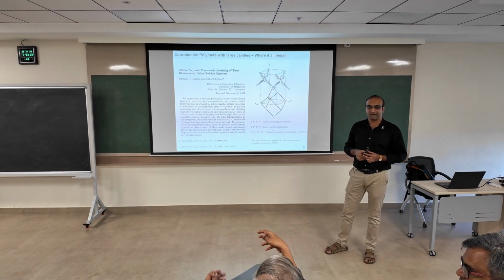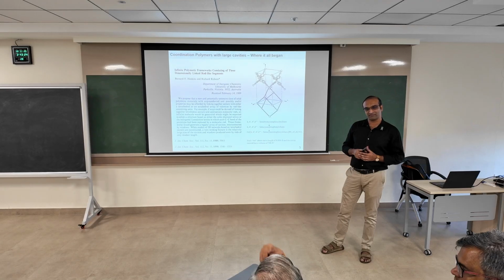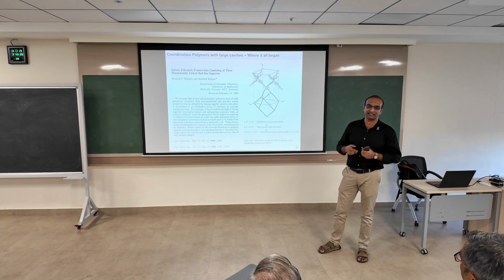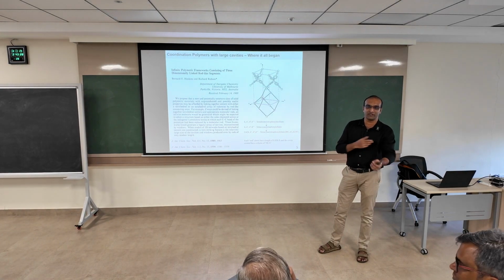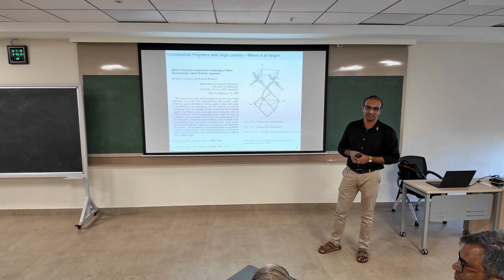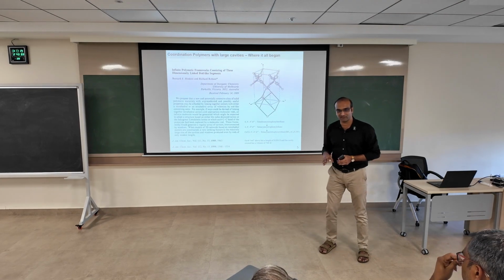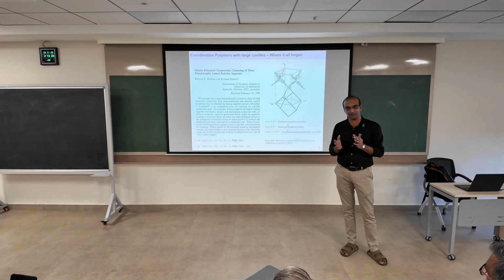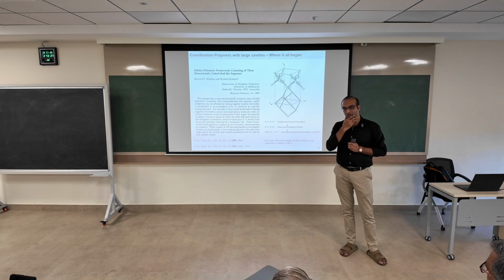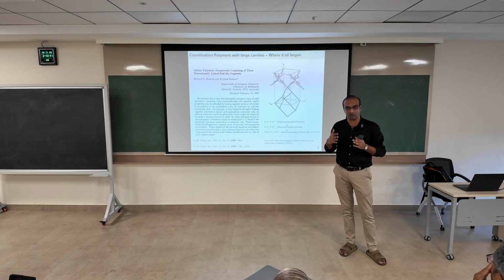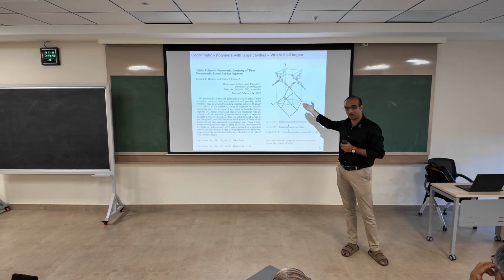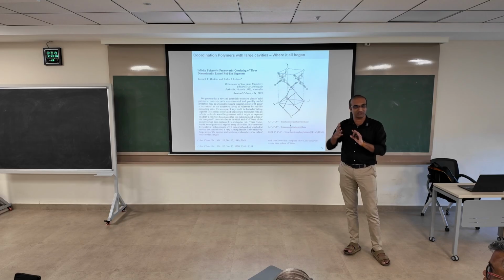Is it a spontaneous crashing? No, something triggers that crash. Basically, if you use an acid, or if you heat the water to say 60 or 70 degrees. Even the first instance of whatever Susumu Kitagawa did was like this. They were not very stable. Now if you want a MOF to really be applicable in many scenarios, it has to be hydrothermally stable, especially when steam or water is coming. Some of these MOFs, if you heated the water slightly, the whole crystal order would come apart.